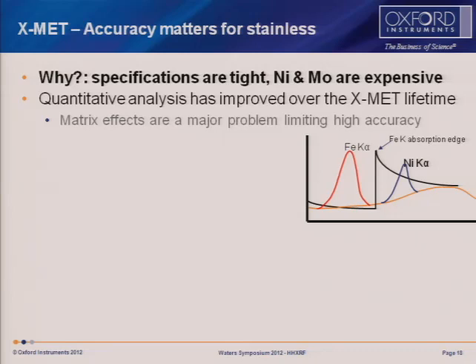So let's talk about what that all does for accuracy and why it really matters. Well, it matters because specifications are increasingly tight. Nickel and molybdenum, which are key components, key parts of stainless steels nowadays, well, they're expensive, in excess of $20,000 per ton around about at the moment. And matrix effects with these materials are really quite a big challenge, and that limits accuracy in a number of ways. But that's improved all throughout the Xmet lifetime.